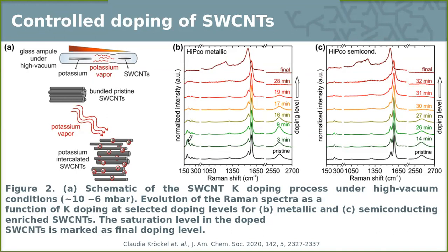So the metallics, now we have a hint about how the behavior of this material goes. We see that the metallic peaks go out first, then the semiconducting ones. So we started to dig into this information to find out why this situation is occurring. Why are we losing one kind of material, the metallic nanotubes, first, and then the other one?